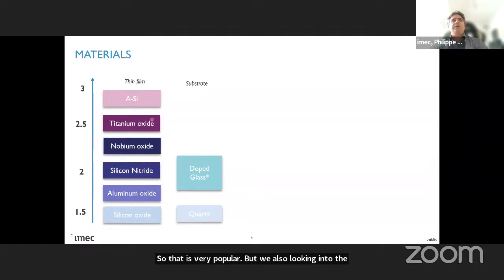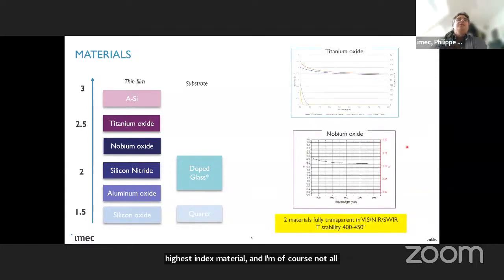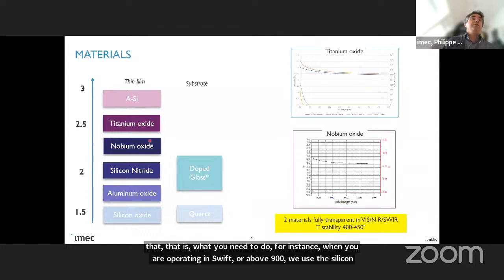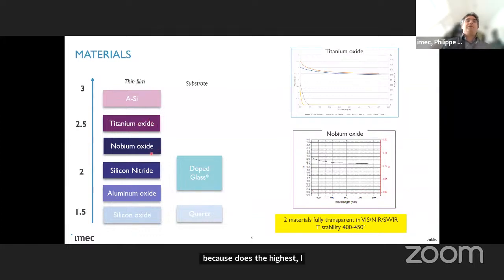But we are also looking into the highest index materials: niobium oxide, titanium oxide, and even amorphous silicon. They are, of course, not all transparent in all the wavelengths, but that is what you need to do, for instance, when you are operating in SWIR or above 900. We use silicon because it has the highest index. Otherwise, we start to use a material like titanium oxide and niobium oxide.